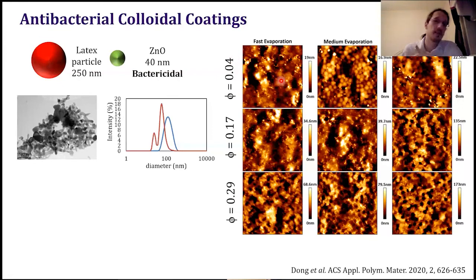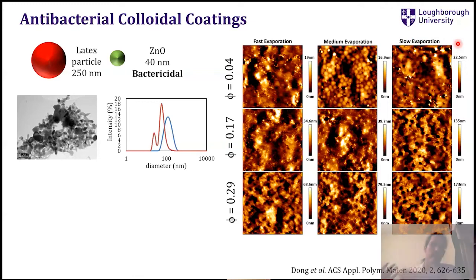So fast evaporation rate is drying really fast under an infrared lamp. Medium evaporation rate is just letting it dry in a normal indoor environment. And slow evaporation rate is letting it dry in a really high humidity chamber. It's about 95% relative humidity, which takes several days to dry versus a couple of hours or 3 hours in indoor conditions.